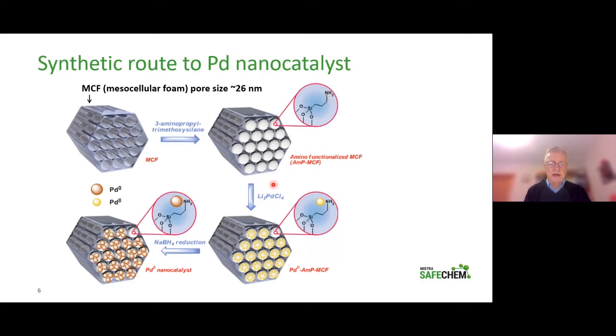So we add palladium 2 here, and the palladium 2 is binding nicely to the amino group. It's a very strong bond actually between the amines and palladium 2. And then subsequently we reduce it with sodium borohydride to get these nanoparticles as shown here. And this is our nanopalladium catalyst. It's active nanoparticles of palladium.